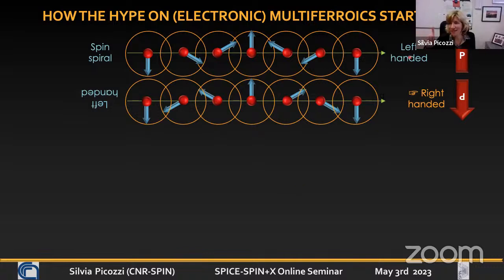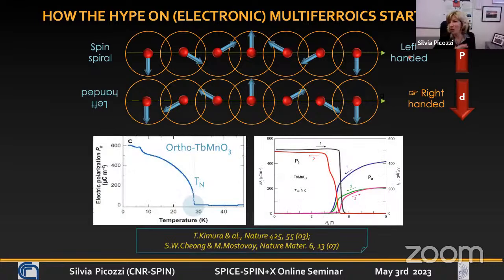So you have a polarization, ferroelectric polarization, with spin cycloid left-handed, and opposite if you switch the chirality. And this was well proved in 3D systems, mainly manganites, oxide, correlated materials. So it was very clear that you have electric polarization below the magnetic ordering temperature. So the connection between magnetism and ferroelectricity could not be doubted. And this, of course, was a source of nice physics and a lot of attention from the scientific community.